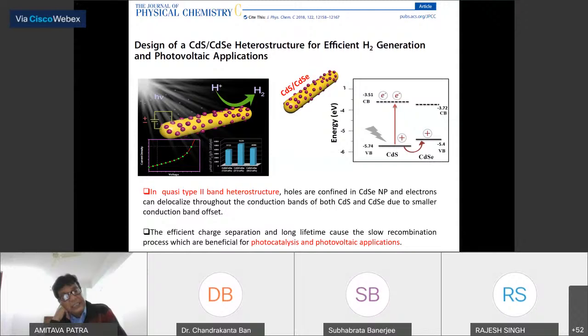This is a cadmium selenide nanostructure material. This is a cadmium sulfide rod and cadmium selenide dots over there. Why have we done it? There is a band diagram. This is the cadmium sulfide band. This is cadmium selenide. This is a quasi type 2 band structure, because if you excite this, then the hole goes from the cadmium sulfide to cadmium selenide, and this is all delocalized over here. So there is a chance of charge transfer, and you can separate the electron and hole.